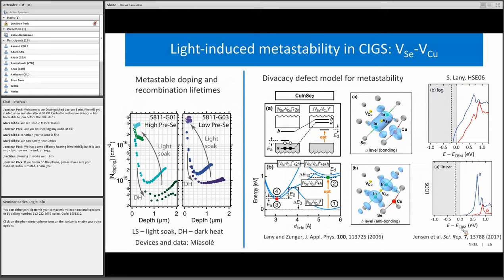The pictures and illustrations on the right show the explanation developed by Stefan Lany and Alex Zunger at NREL for this effect quite some time ago, where from first principles analysis, these researchers identified that copper and selenium divacancies are the metastable defects. They could be in plus or minus state, and they transition between these plus and minus states because of exposure to light. One of these states, the minus state, has higher doping, but also shorter lifetime. The plus state is the one where you get after being in the dark. The cartoon made by Lany and Zunger has this orange arrow, which suggests an experiment to verify the presence of this feature, in that one needs to use light that is less than the band gap and directly measure the transition to the plus divacancy state.